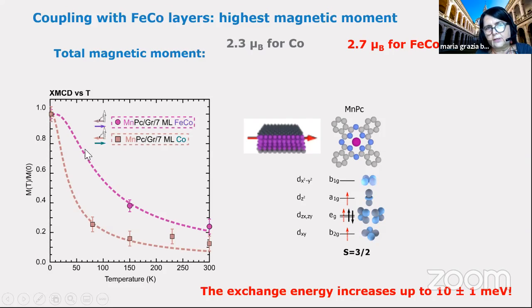In this case, you will have an even higher magnetic saturation of magnetization at room temperature. So this is a very good result. And then also the exchange energy increased up to 10 millielectron volts. It is a good value for a molecule, no?